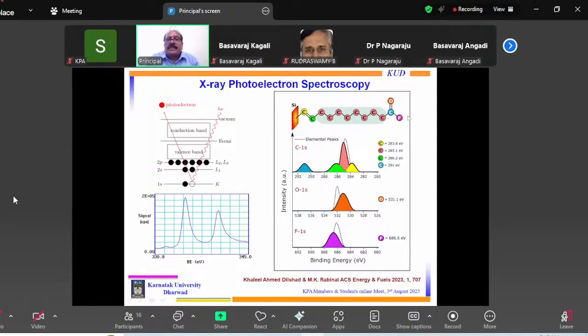Here it is just an example. The cartoon was created by ourselves for the review article, just to give a feeling of how this technique can actually sense. Suppose you have an example of this molecule and there is a silicon. By chemical reaction, you have bonded this molecule. There is a carbon and silicon bond. This molecule has 1, 2, 3, 4, 5, 6, 7, 8, 9, 10, 11 carbons. At the end, you have oxygen. There is a fluorine. But if you look carefully, these carbons are sitting under different conditions. The chemical environment is different for these carbons. For example, this carbon is bonded to silicon. It has one environment,